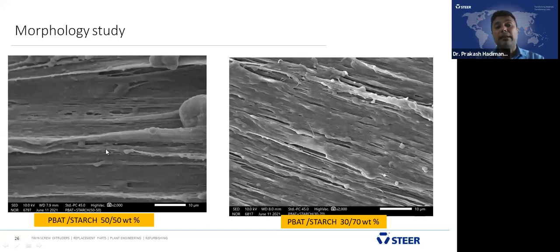That shows the complete homogeneous, no fractured surface, which means there is homogeneity in the blend. That's why there are no voids, and we get better elongation and impact strength. These two were observed. And at 30-70, at 70% starch, because there is only 30% of PBAT, we could observe slight fractured